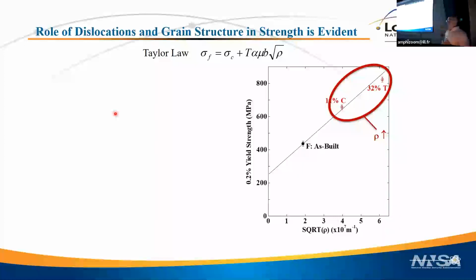And according to the Taylor law, which is older than most of the people in this room, if not all, that should be a linear relationship, right? And first I'm just showing you, this is as-built material versus material that's been deformed. This was, I can't see the number, I think 11% in compression and 32% in tension. And you can see that nice linear behavior as the dislocation density goes up from deformation. The reason I show that is if you're just deforming it, you can be pretty confident that the only addition to the peak width is dislocations. If you're deforming it, you're not changing chemistry.